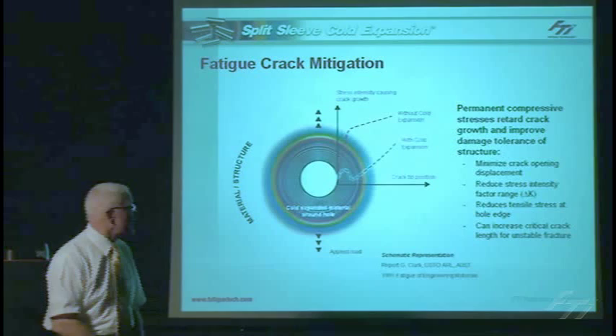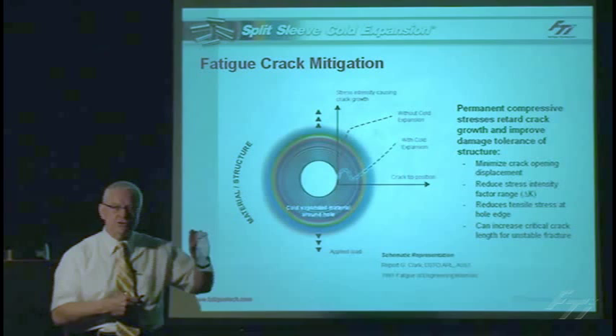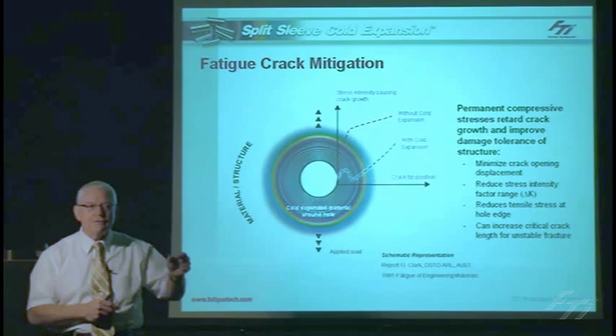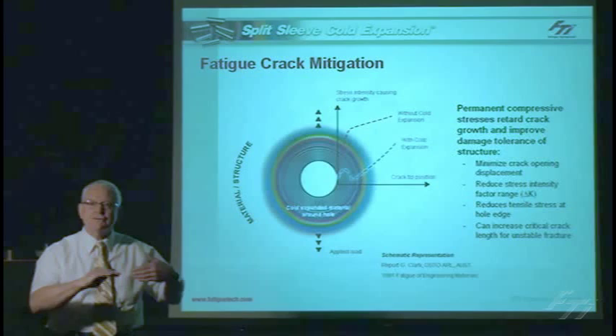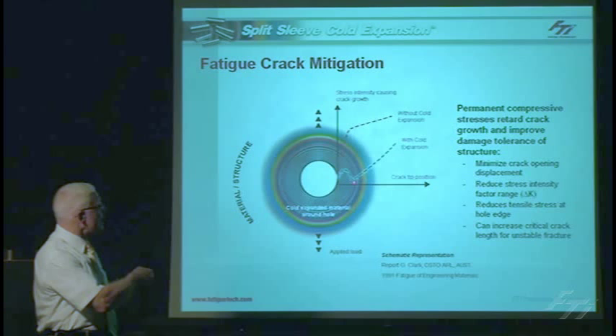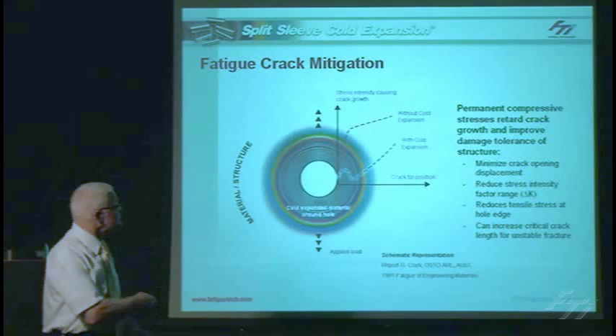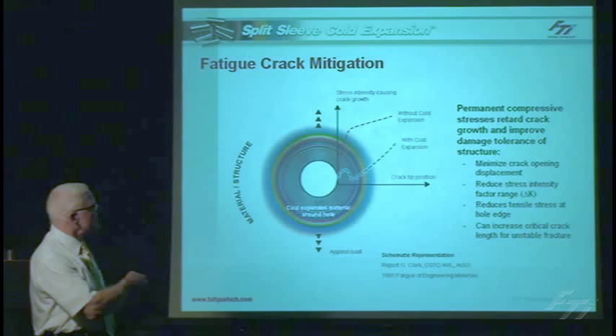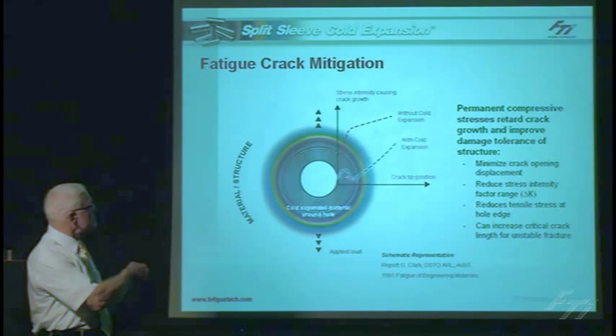Part of the reason it does that is that we have a stress concentration — a factor of about three times the stress just by drilling the hole. Now if you have a crack in the hole, we have another multiplying effect on the stress called the stress intensity factor. That stress intensity factor, as a crack grows from a hole, will typically increase and continue to go until you reach the critical crack length, which will cause the crack to actually fail the structure. If we cold expand the hole, that clamping effect of closing the crack up will greatly reduce the stress intensity factor, as shown in the analytical results.